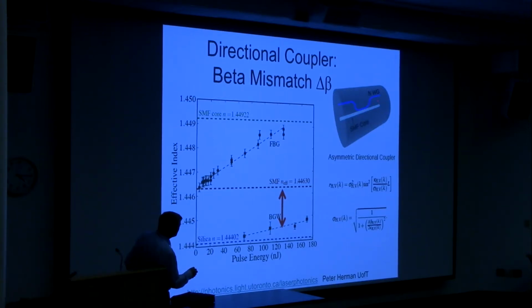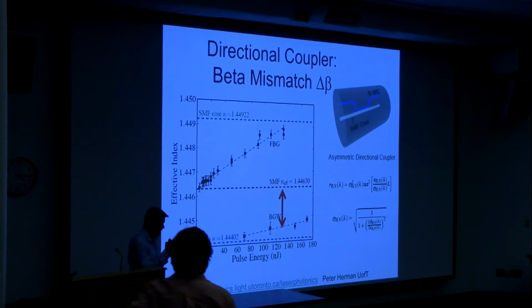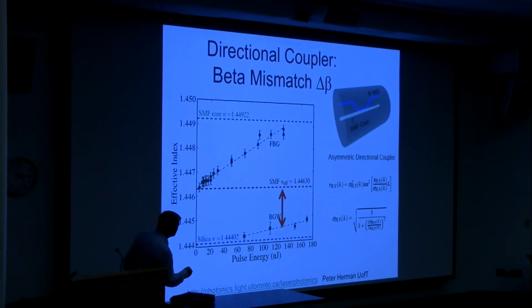So, this coupling isn't automatic, and the reason is that you need to have the same effective index. The refractive index of the core waveguide is this effective value here, 1.446, just a bit more than that. The glass around it has this refractive index, and the germanium core has a higher refractive index. So there's the starting point for the core waveguide. There's the starting point for the silica. When we laser write waveguides, we need higher energy, and so we can increase the refractive index of the waveguiding effective index like this, but it never reaches the effective index of the germanium doping. And if we modify the germanium, it just increases as well.